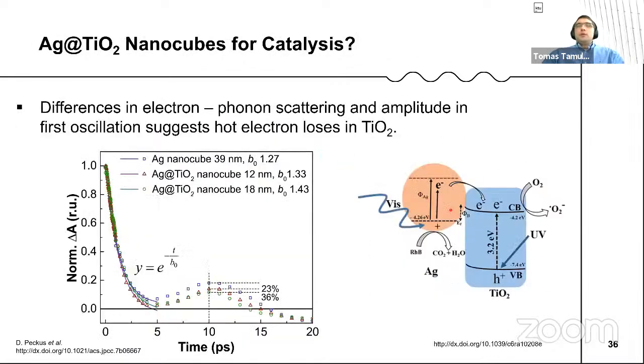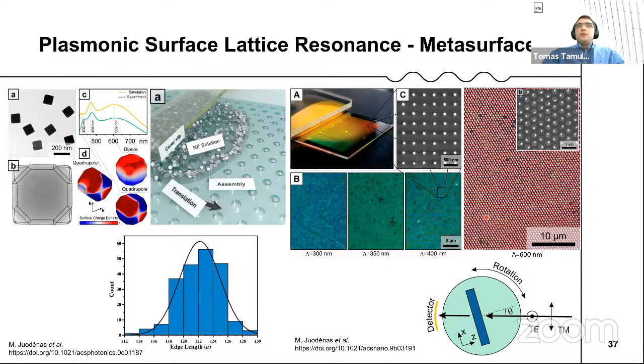Maybe I will skip this because I'm a bit running out of time. And what we noticed is that if we have this titania of a different thickness on those core-shell structures, we have different decays and slightly different amplitude of those oscillations. So we think that there is some energy transfer between the electrons in this plasmonic nanostructure and this TiO2 we have on top. Okay, so I'm now coming to this surface lattice resonance.